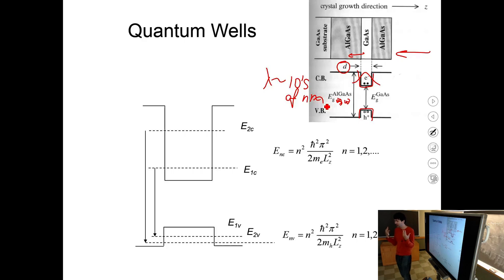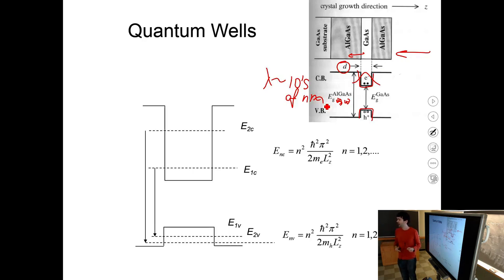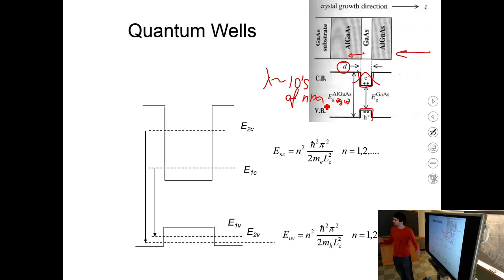The electron wavelength spans many many atoms. In gallium arsenide you can think of an electron occupying a volume of 10×10×10 or 20×20×20 nanometers. This is also because the density of electrons is very low in these semiconductors — intrinsically pure gallium arsenide should have zero electrons at low temperature. With thermally activated electrons there can be some density, but the ratio of electrons to atoms can easily be a million or a billion. That gives you tens of nanometers volume per electron.